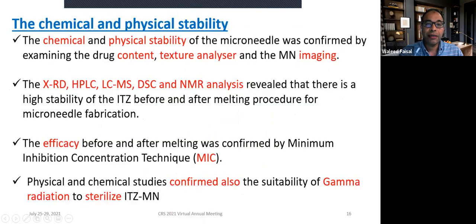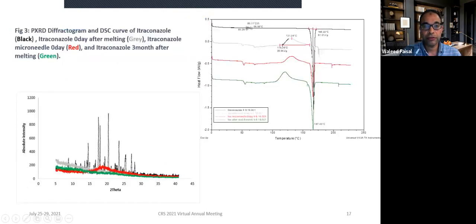So when we look at chemical and physical stability, it was confirmed by drug content, texture analyzer, and imaging, and we also used XRD, DSC, LC-MS, HPLC, and NMR to confirm the stability. To confirm the efficacy, we used the minimum inhibitory concentration technique, and we confirmed the suitability of gamma radiation to sterilize the microneedles.